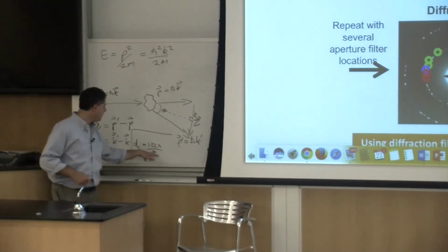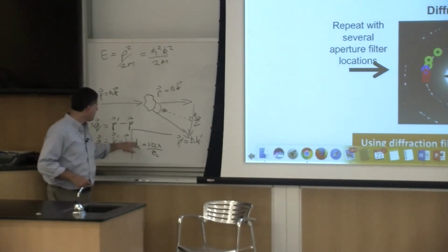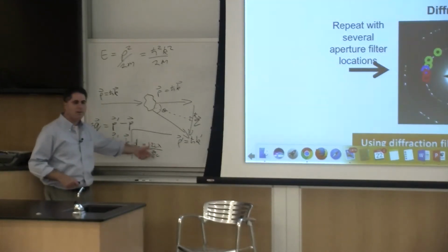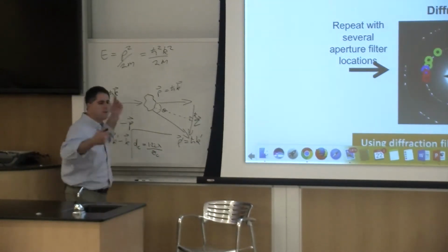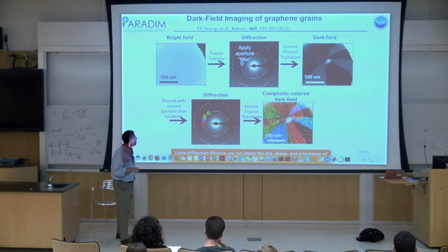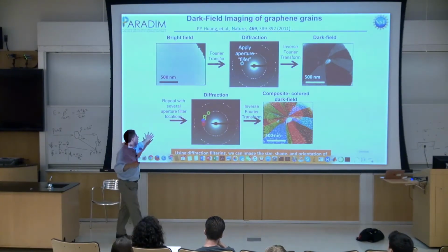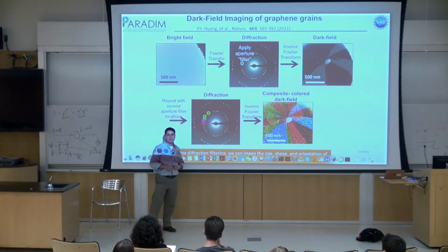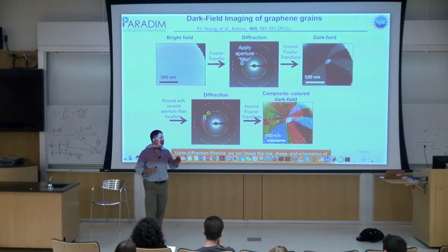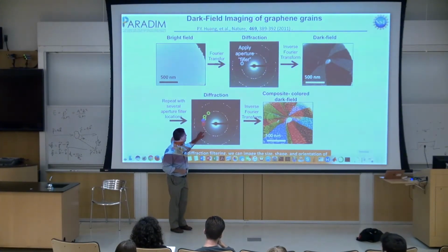So if this is DC, this is 1 over k cutoff. If 1 over k cutoff is a tenth, then DC is 10 times. So the dark field imaging method you're going to work with this afternoon has an intrinsic resolution limit, which is it's got to be worse than atomic, and it's probably 10 to 20 times worse than atomic. The tinier you make your aperture, because you want to get that spot and the one next to it, the smaller you make your aperture, the worse your spatial resolution becomes.